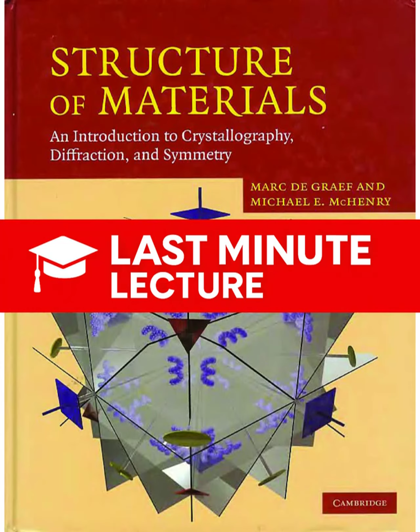Gone. Okay, next up is the body-centered lattice. We add an atom at 1/2, 1/2, 1/2, the very center of the cell. I-centering imposes an even stronger constraint. The math works out such that the terms cancel when the sum of all three indices, h plus k plus l, is an odd number. So h plus k plus l must be even? That's the rule. And this systematic pattern immediately identifies the lattice as body-centered. Reflections like 110, 200 in this case.